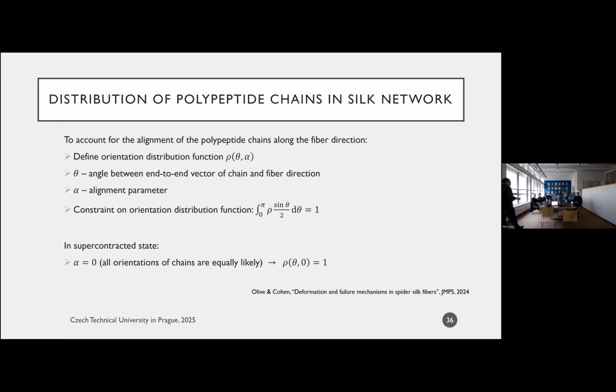When I put it in water, I break these intermolecular bonds. All of the chains start to gain entropic freedom. They start moving around, they gain mobility, and the order gets lost. I end up with a structure with chains that are randomly oriented and uniformly distributed. If I stretch it and then let it dehydrate, I'm forcing the structure to find its equilibrium. I'm forcing the intermolecular bonds to form in a situation in which the chains are more stretched. So basically, I'm controlling the alignment of the network.